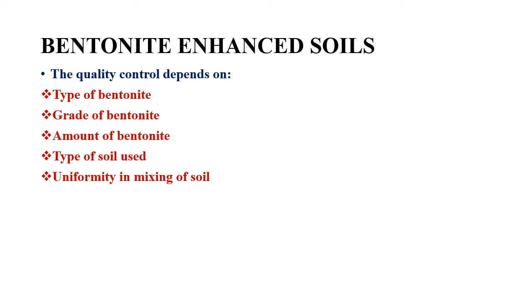So, it is seen that calcium bentonites have a very low free swell compared to sodium bentonite, and usually we term a bentonite as high grade or high quality if it has free swell values in the range of 18 to 28 cc. Okay, so that is how we classify bentonites based on their swelling capacity.